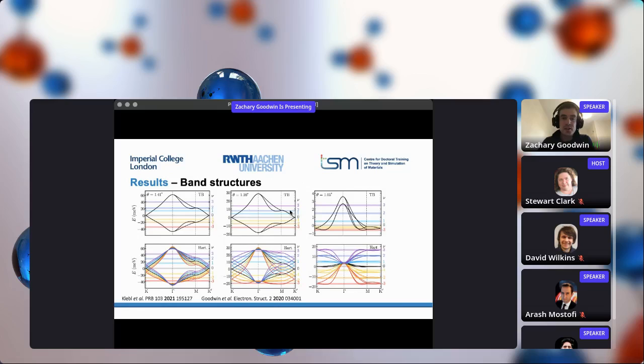Right, so we can look at the results of this interacting theory. In the top panels, I'm just showing the tight binding results. There are no electron interactions in this theory, and essentially what doping does to this system is just change where the Fermi energy resides in these flat electronic states. In contrast, upon including these Hartree interactions, what we find is that there is an extremely sensitive dependence of the electronic structure on the doping level in the system. When I add electrons to the system, so if I'm adding 1, 2, or 3 electrons, the states at the edge of the Brillouin zone, so M, K, or K prime, shift up in energy relative to the states at the center of the Moiré Brillouin zone.